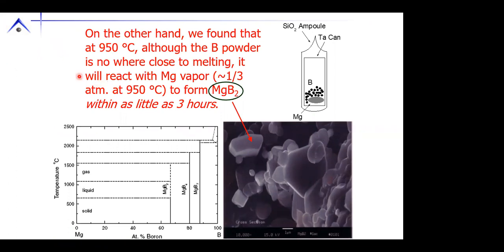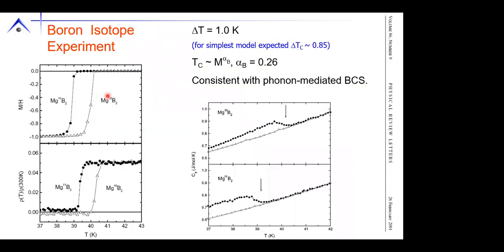And in this case, what we could find is that in as little as a few hours at 950, we can have magnesium vapor diffuse into high purity boron, and we can get high purity MgB2. And since we had high purity isotopic boron around, we can immediately look at the isotope effect. We can see it in magnetization and resistivity and specific heat. There's a 1 Kelvin shift in Tc as we go from boron 10 to boron 11,